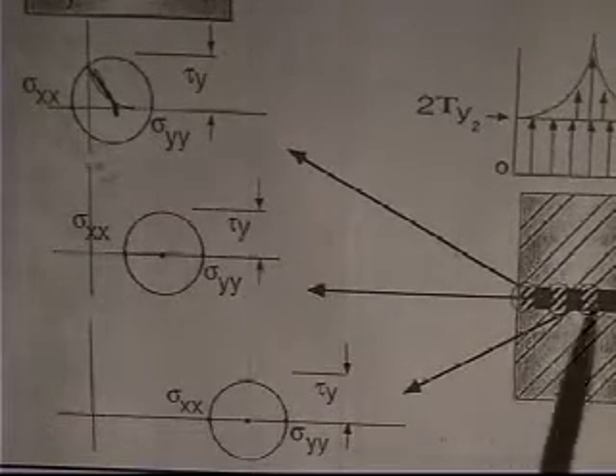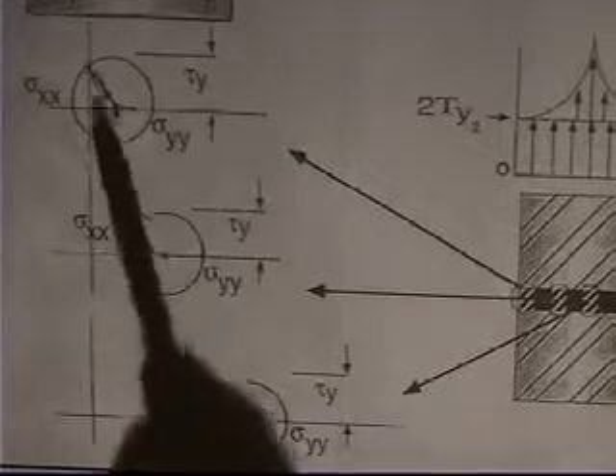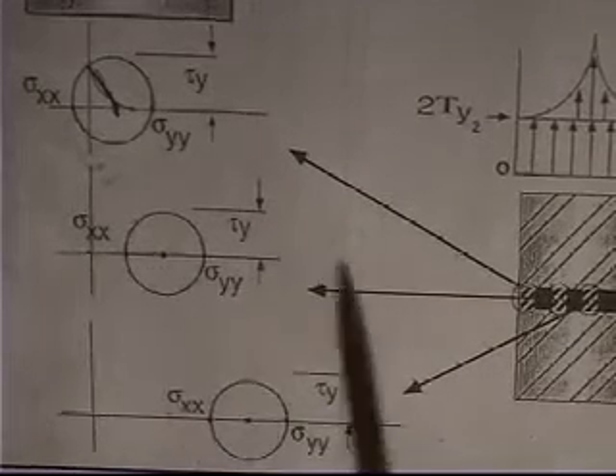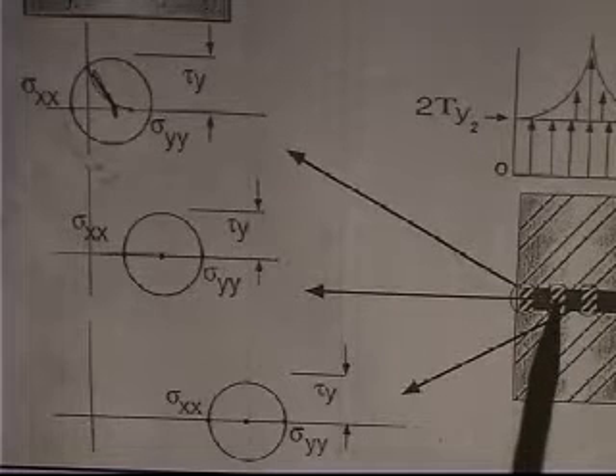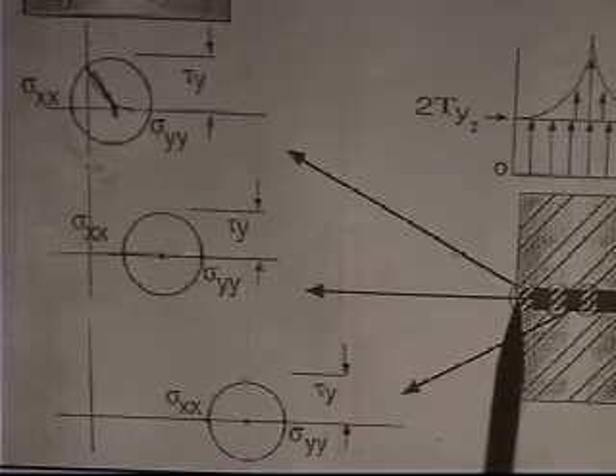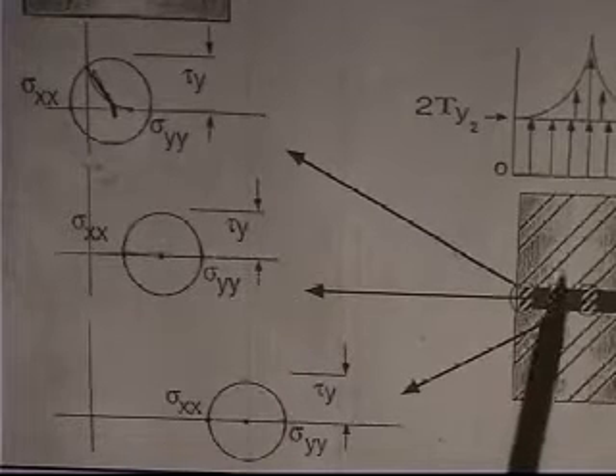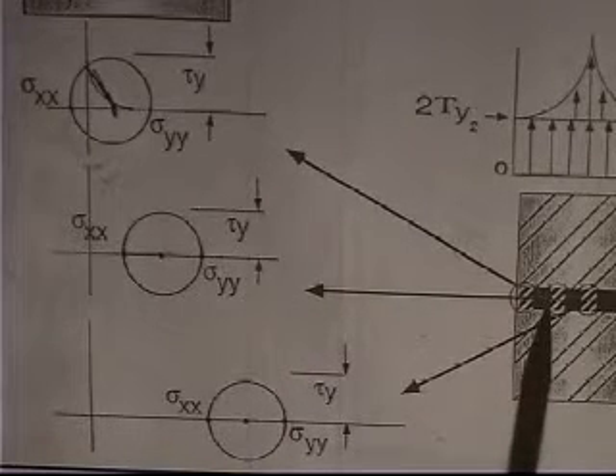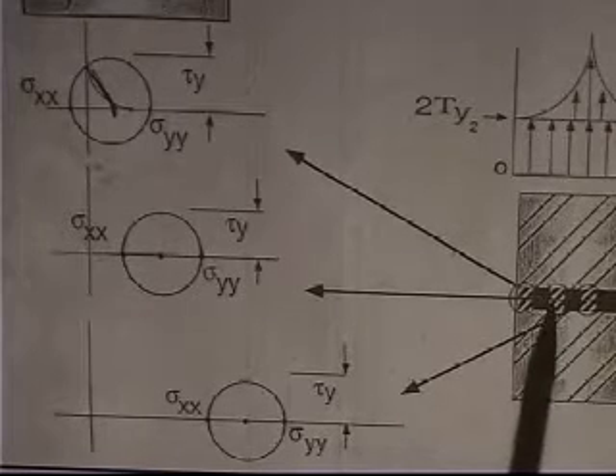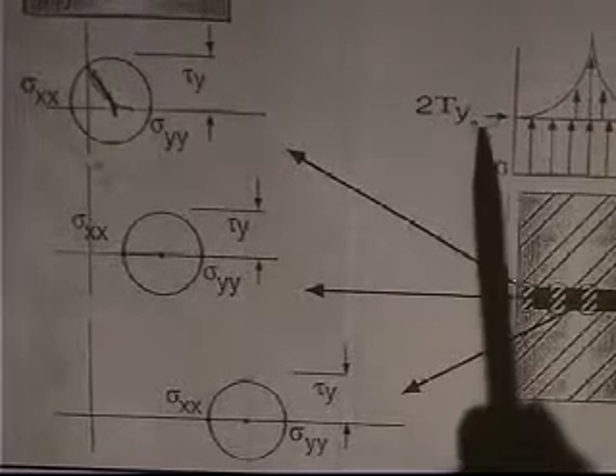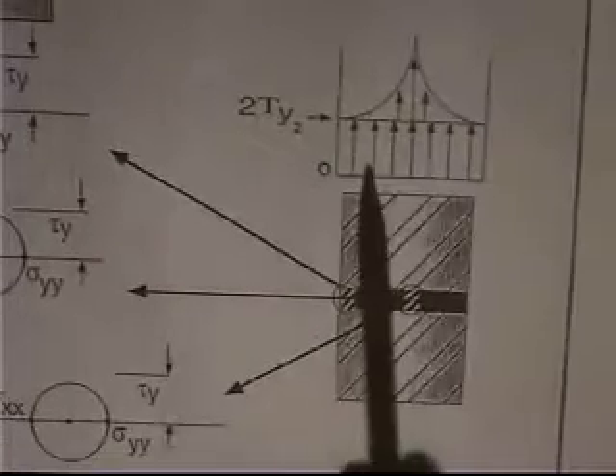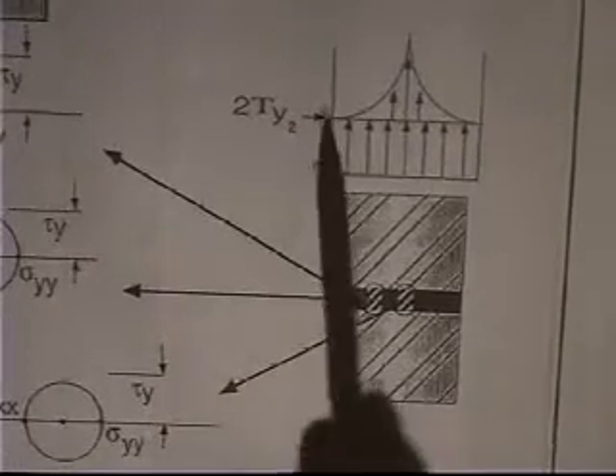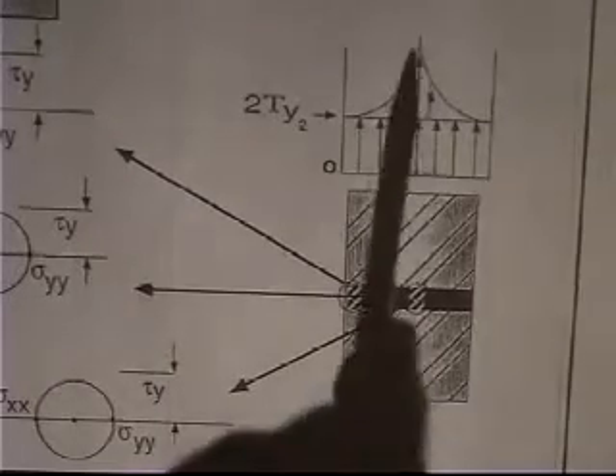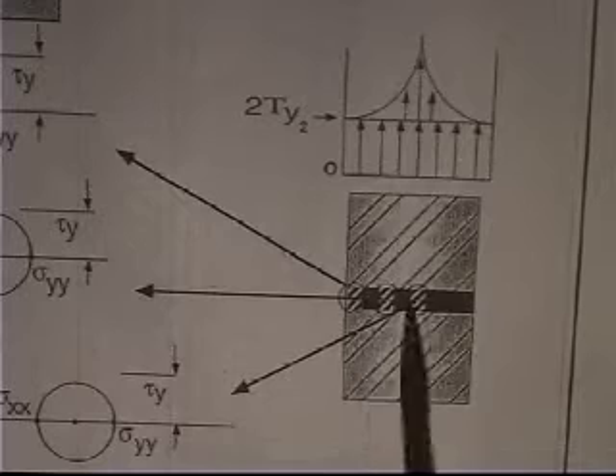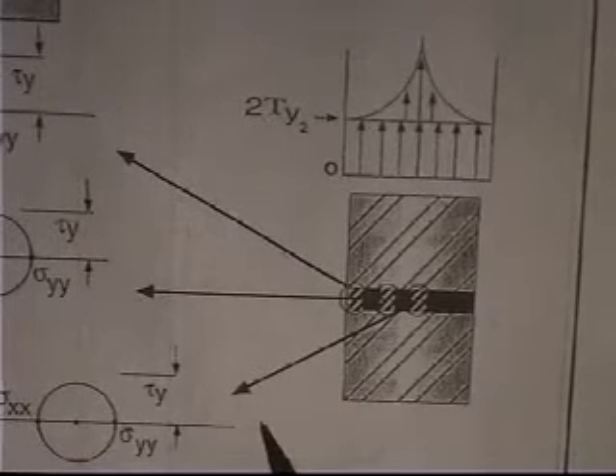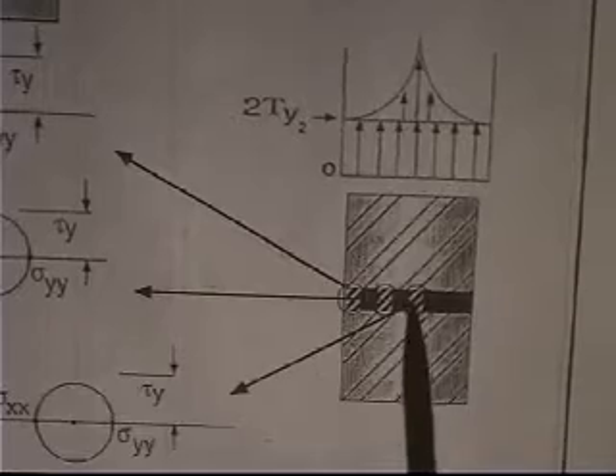However, as you start marching in towards the center, the Mohr circle, which doesn't change in diameter, starts marching out this way. And the reason is I end up getting triaxial stresses. Here, I simply have biaxial stresses. There's no stress at the surface. But as I get in here, I'm squeezed from all directions. Actually, I'm pulled from all directions in this case. It's a tensile triaxial stress. And what happens is you have a yield stress of 2 tau y in tension, which is this level right here, but the exponential we're talking about adds a triaxial stress on top of this that looks like this. And as you go further and further towards the center, the Mohr circle moves further and further out with a hydrostatic tension in the braze alloy.